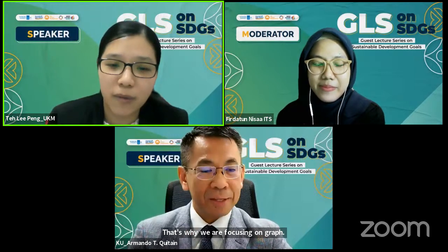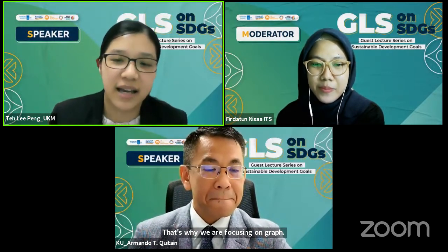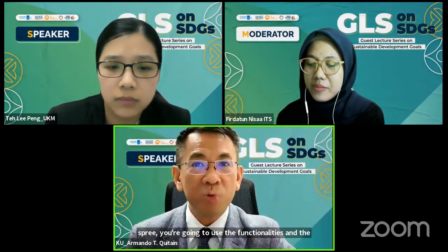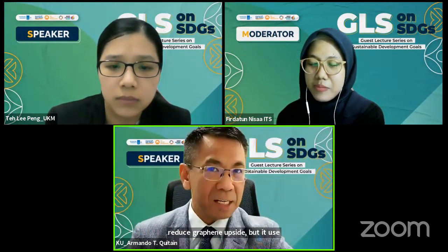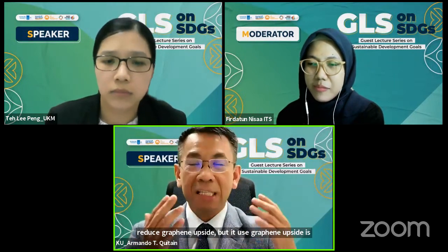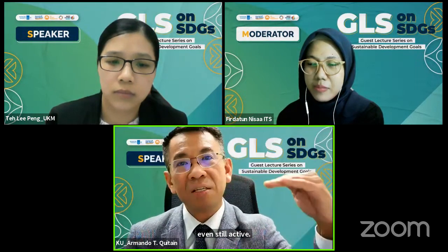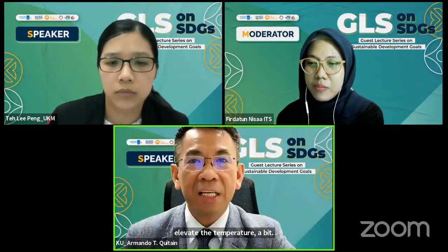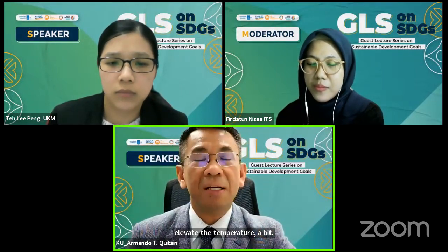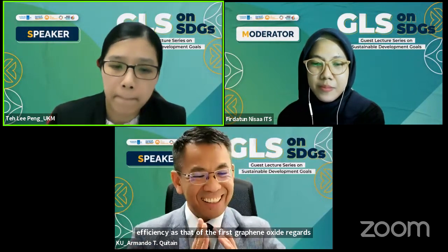Okay. Because nowadays people are doing more research on reduced graphene oxide and graphene oxide. Well, the graphene oxide is not so stable, especially at a high temperature of around 160 degrees centigrade, where you lose the functionalities on the surface. And losing those functionalities, you get the reduced graphene oxide. But reduced graphene oxide is still active, and it's stable even at higher temperature. You can elevate the temperature a bit above the normal temperature, utilize the reduced graphene oxide, and you'll get almost the same efficiency as that of the fresh graphene oxide. I see. Regarding carbon dioxide adsorption capture, we also did a nitrogen functionalization of reduced graphene oxide.